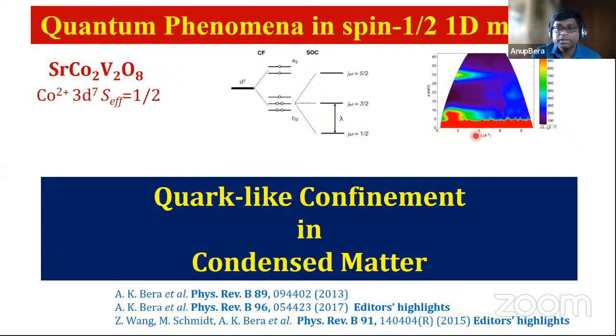And this is experimentally proved by neutron inelastic scattering. When we do the scattering, we see around 30 milli-electron volt a crystal field excitation. And this energy is equivalent to the transition between J effective 1/2 and J effective 3/2 states. It gives the confirmation that indeed we have effective spin half.